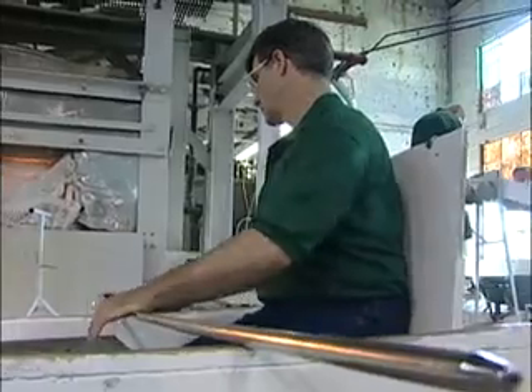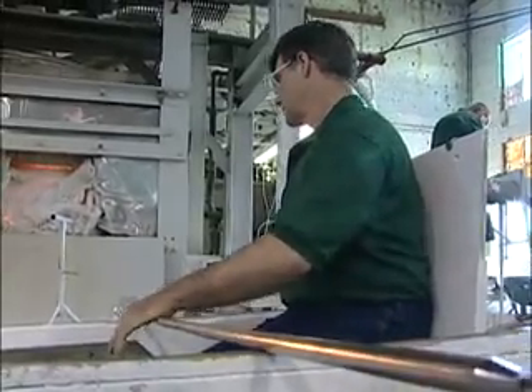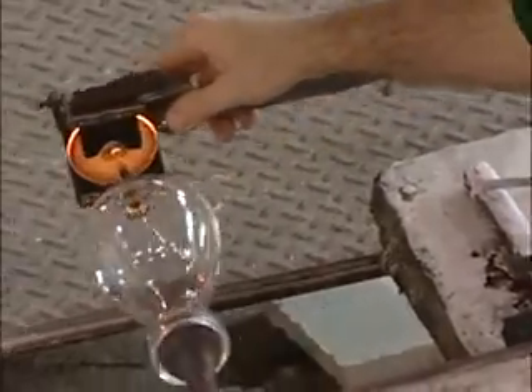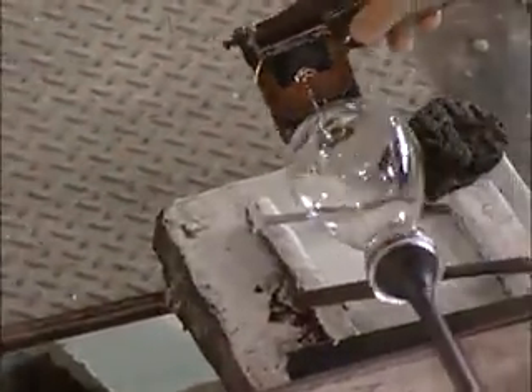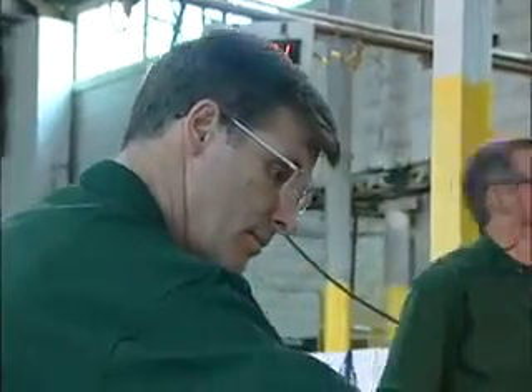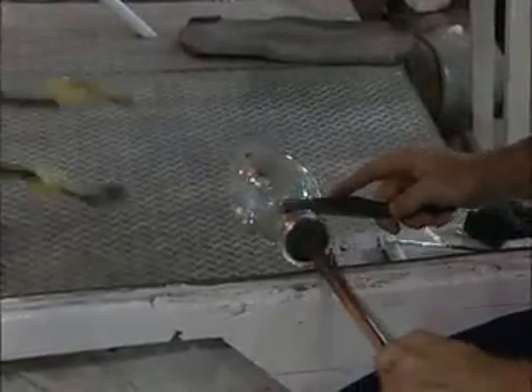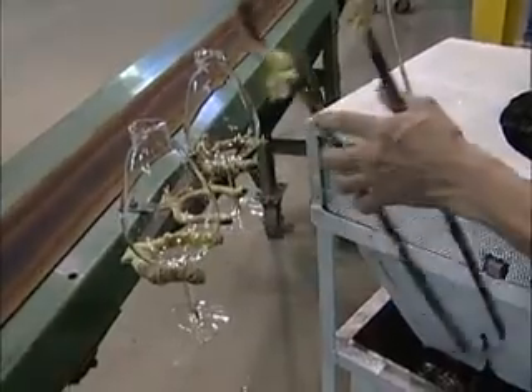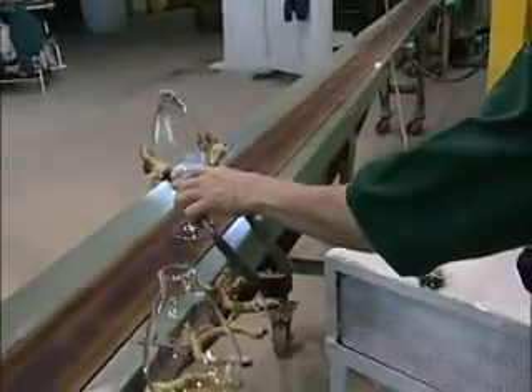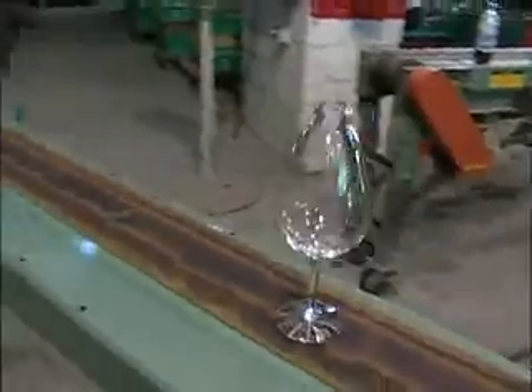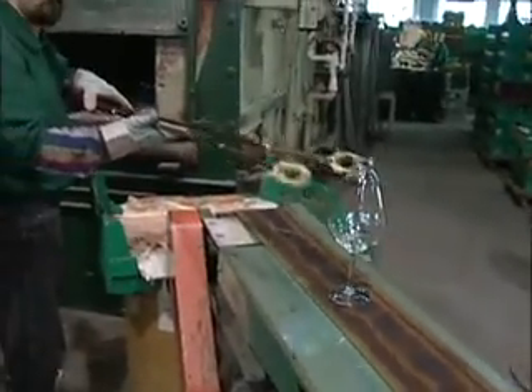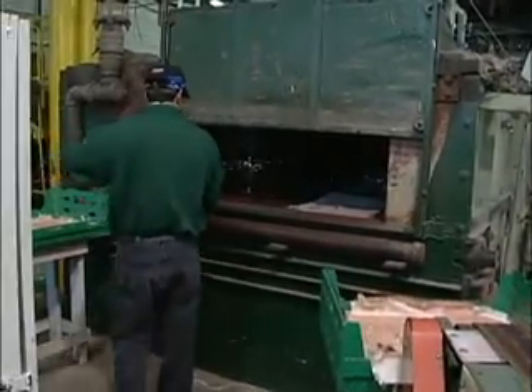Again, the glass must be constantly rotated to avoid runoff. Using a tool called a clapper, the stemware finisher rolls the foot out to the exact size, aligns the foot to the stem and bowl, and cracks the fully blown piece from the blowpipe. The rapid cooling of the glass from its molten state develops stress in the piece, which must be relieved before further processing. That's accomplished through an annealing process, which reheats the glass and then slowly cools it in an oven called a lehr. This 90-minute process relieves stress and prepares the glass for the first of 4 quality assurance inspections.